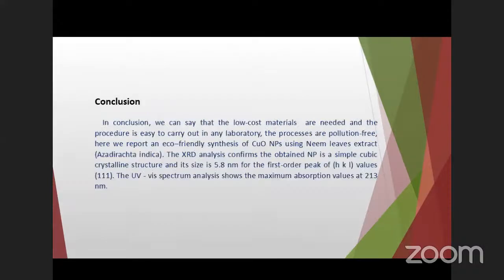In conclusion, we can say that the method is cost effective, eco-friendly, and easy to operate in any laboratory. By characterizing our sample, the XRD analysis confirms the nanoparticle is obtained and the highest absorption value is obtained at 213 nanometers, and the size of nanoparticle is found to be 5.8 nanometer for first order peak value.